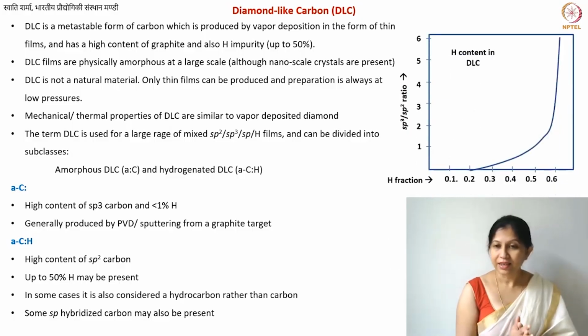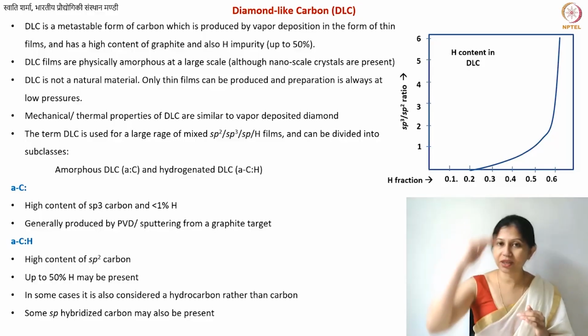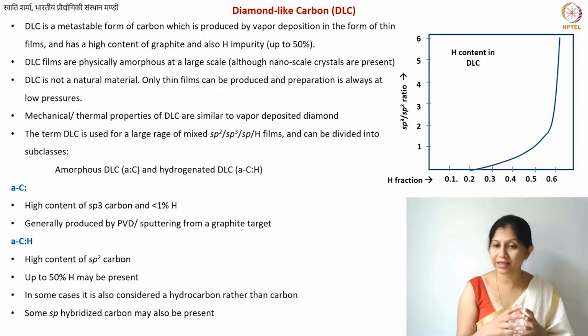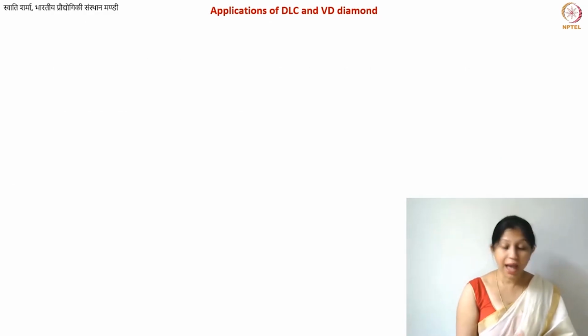Here in this diagram, you can see the hydrogen fraction, 0.1, 0.2, and so on, and then you have the sp3 to sp2 ratio on your y-axis, and you can see how it increases. So there is a balance between this sp3 to sp2 ratio and the fraction of hydrogen in the case of amorphous hydrogenated DLC. Now coming to the applications. The applications here are for both DLC and vapor deposited diamond, and these are just some representative applications. Of course, you can find some other applications too.